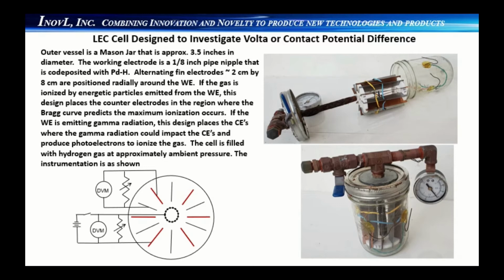Alternating fin electrodes are approximately 2 centimeters by 8 centimeters and positioned radially around the working electrode. If the gas is ionized by energetic particles emitted from the working electrode, this design places the counter-electrodes in the region where the Bragg curve predicts the maximum ionization would occur.